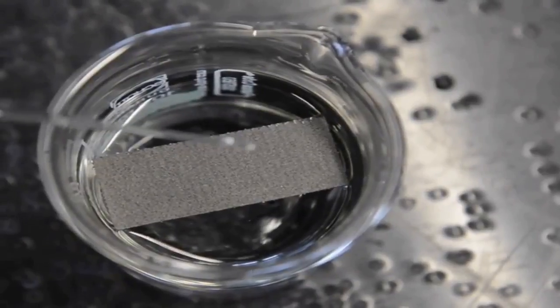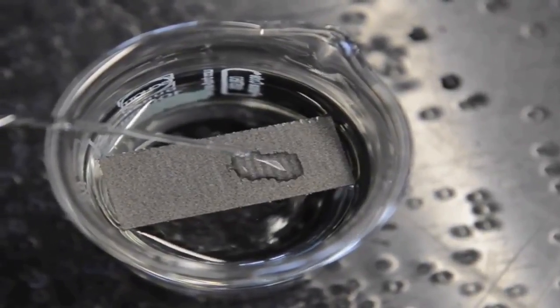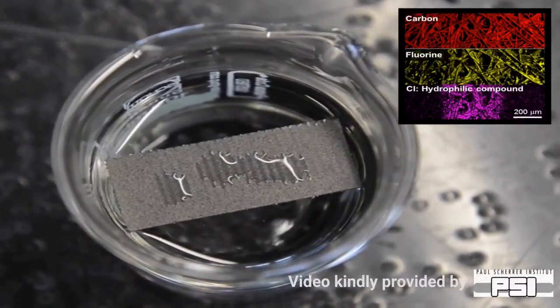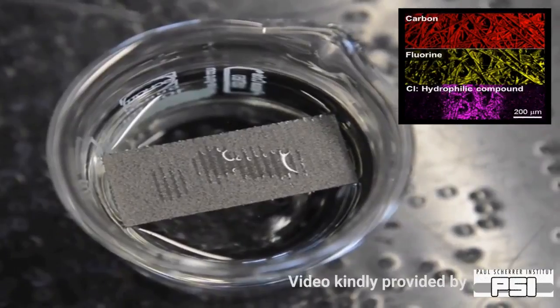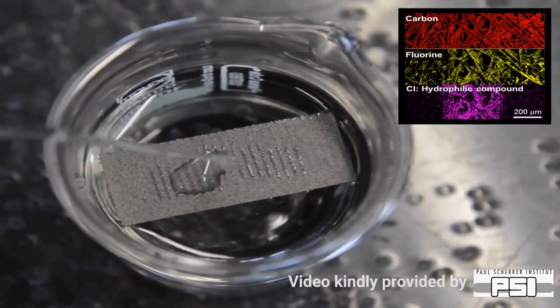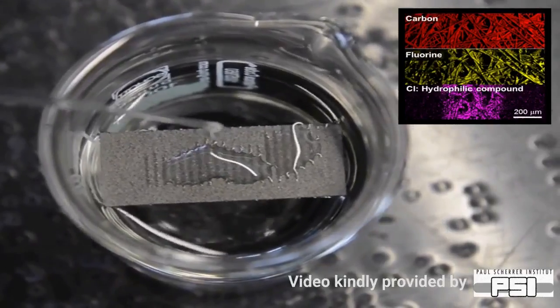Thanks to the hydrophilic domains, water concentrates in the channels designed for that purpose, as can be seen in this video. On the upper right side, you can see an energy dispersive x-ray analysis showing the elemental distribution. The chlorine signal indicates the presence of hydrophilic polymer.